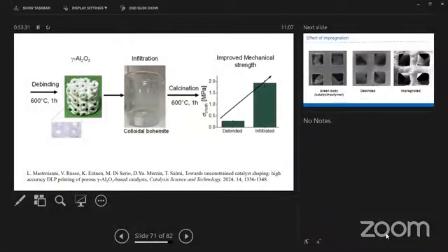So we print the body, and then the next step is to put some sort of a coating of boehmite on top of this gamma alumina. And then once again calcination. So we have 2 calcination steps. And that is the way to make something relatively mechanically stable. After infiltration, we improve dramatically the mechanical strength.